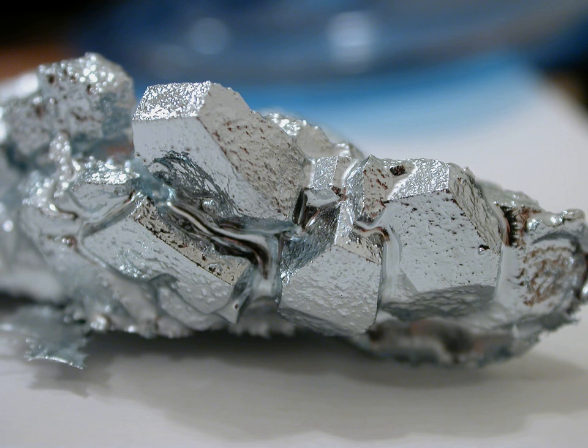Gallium is removed from the ion-exchange resin in solution. Electrolysis then gives gallium metal. For semiconductor use, it is further purified with zone melting or single crystal extraction from a melt. Purities of 99.9999% are routinely achieved and commercially available.